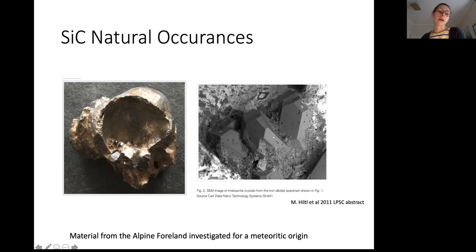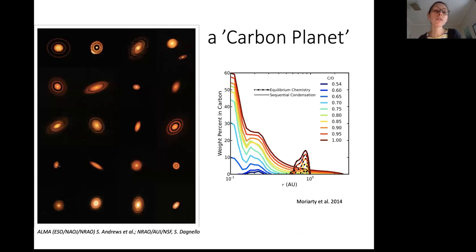So this image here shows material from the Alpine Foreland that was being investigated for a meteoritic origin. And it has a nice SEM image of these silicon carbide crystals, these moissanite crystals. Because silicon carbide is usually associated with pre-solar grains, when you see it in a rock formation, you think this could be a meteorite. Right, and so what really captured my attention was thinking about silicon carbide as a major planetary building block rather than just an accessory phase.